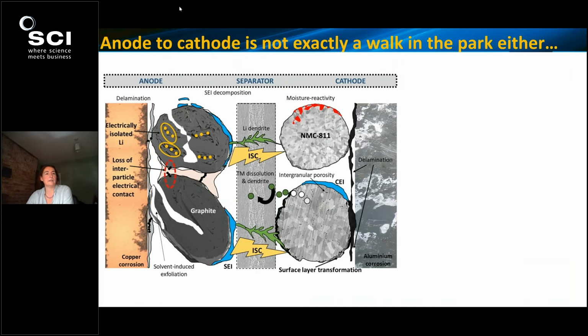So this is a reasonably simplified cross-section of a full cell that you'd find within a battery. From the left, we have the anode, the negative electrode. The current collector for the anode is made of copper, and this can corrode. The electrode coating containing all of the active materials that are adhered to this to convey effective charge transfer can also delaminate as a function of aging. The active particles themselves can exfoliate and start to break down. They can trap isolated lithium, and with the constant SEI decomposition, they can plate out lithium.